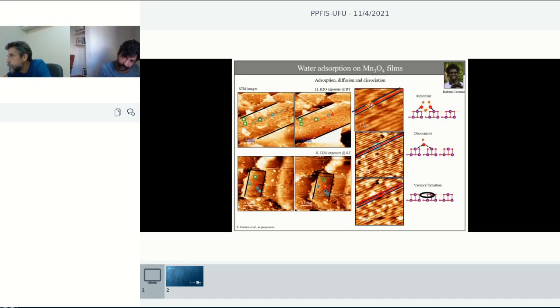If it's on top of the line or in between lines, then we know the structures of this line. And then we can follow, with those different amounts of water and different temperatures, what happened with these structures here. So this is a nice way to see. You see here in these two blue circles, bright protrusions that over here become dark protrusions. So from these changes in the image, we start to assume what kind of reactions are forming or happening.